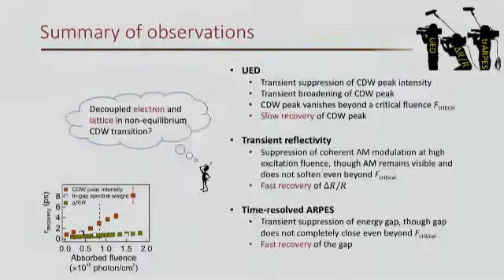Typically, a lattice needs at least a quarter cycle of its amplitude mode, which is around 100-plus femtoseconds, to respond. But for the recovery, we're talking about a time scale of several picoseconds, which is way above the scattering time scale between electrons and phonons. So it's very hard to imagine that the electrons still don't talk to phonons at that time.